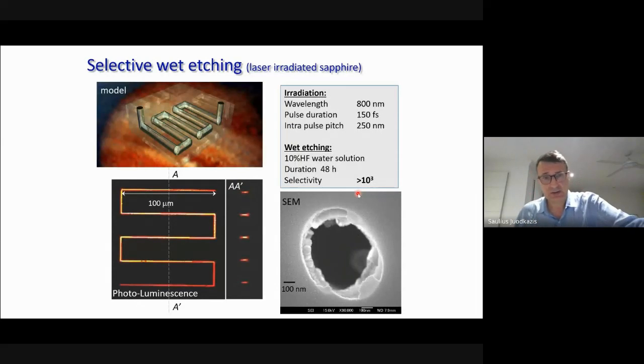So let's look at some applications. This was our earlier work, when we saw that we can recognize modification by actually seeing, after etching, the modified areas. This can be a straightforward application for making microchannels. If you drive modification inside the sapphire with a certain pattern, and then put it into etching solution, because of the very high contrast ratio of etching, you can even keep it for very long hours until all the diffusional process of etching out happens. You recognize that you fabricate very nice channels inside the volume of sapphire. This was visualized simply by putting in rhodamine and making confocal microscopy images.